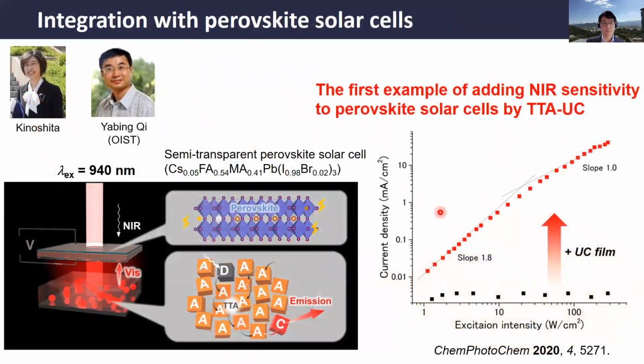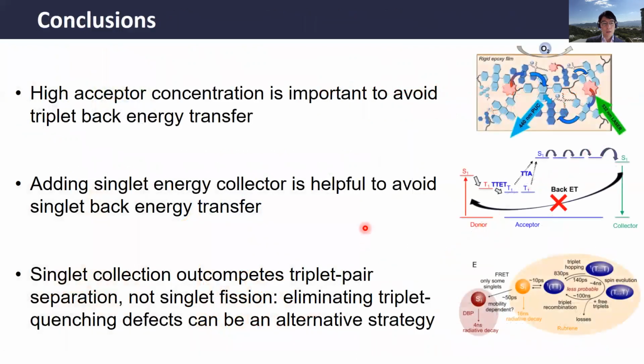and triplet loss. And with this improved three-component system, we combined it with a perovskite solar cell, and we observed a nice near-infrared sensitivity of the perovskite solar cell by using this near-infrared to visible upconversion. Although we need to decrease the excitation intensity further, that is a very important future work direction. So with that, I want to conclude my talk.